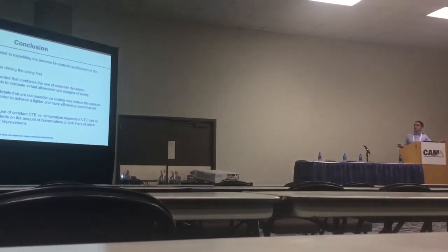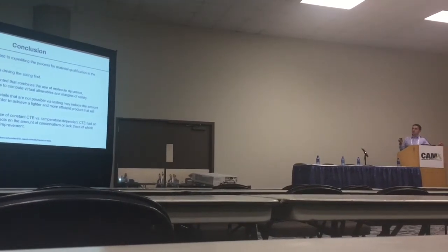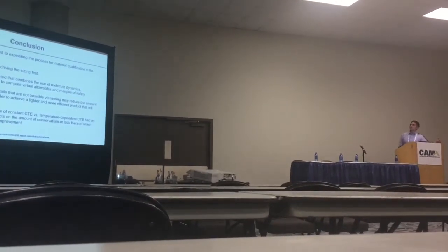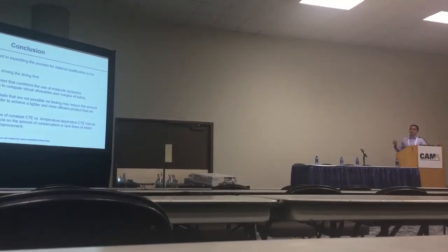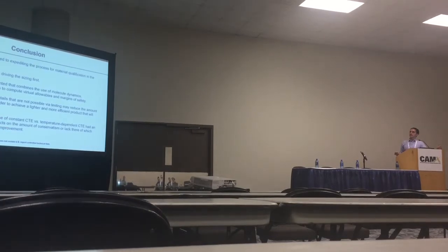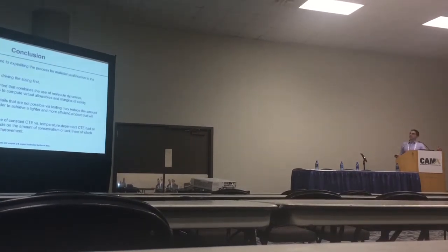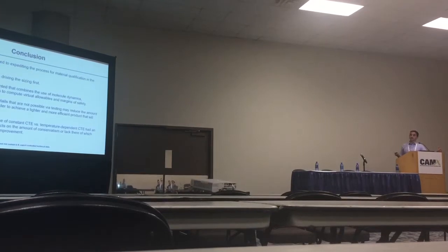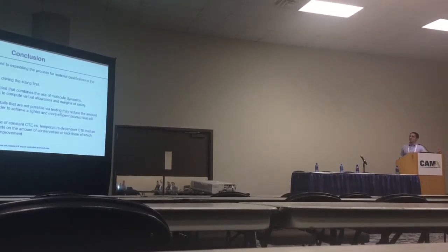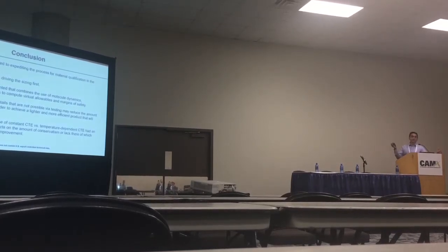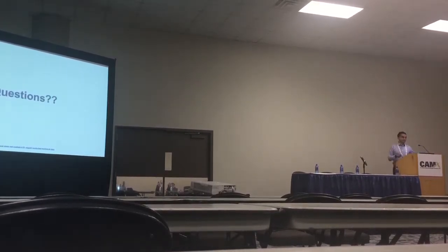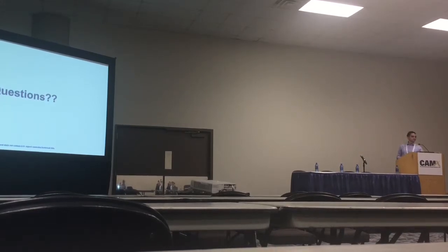Multi-scale work uses MD simulations, micromechanics, and finite element combination to take it from the atomistic scale up to the element or the subcomponent. And you can add additional fidelity, right, to reduce conservatism or lack thereof in the analysis. And we noticed that using a constant CTE versus a temperature dependent one did make a difference in the loads and the allowables that you saw. So, of course, if anybody has more questions, I'll be happy to clarify.